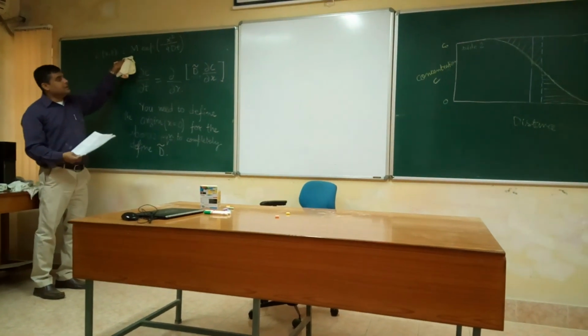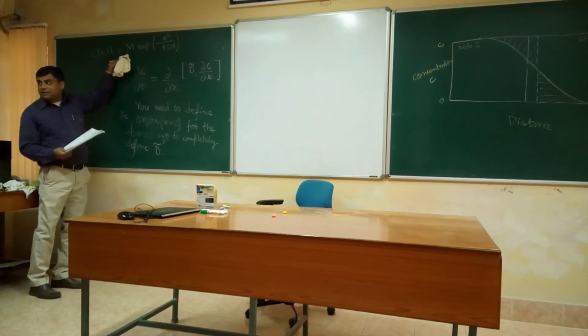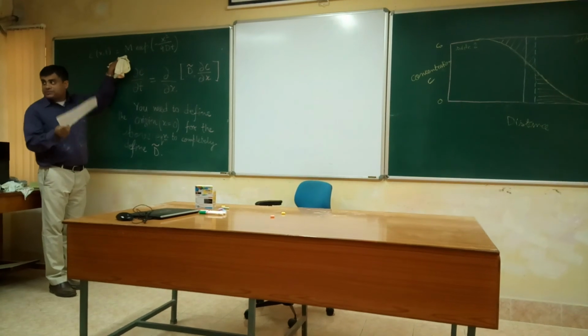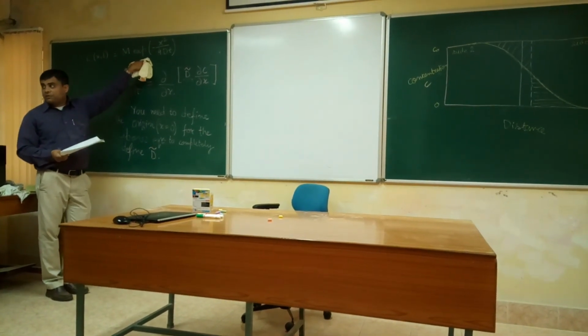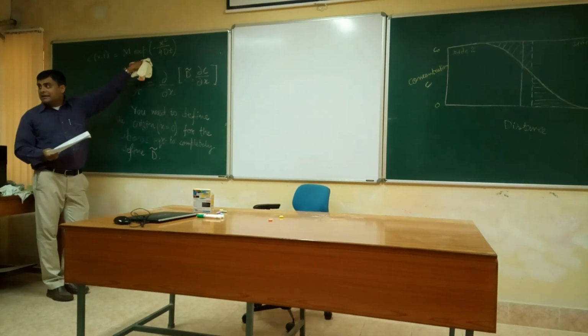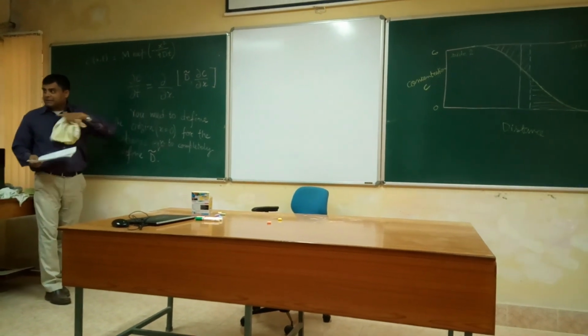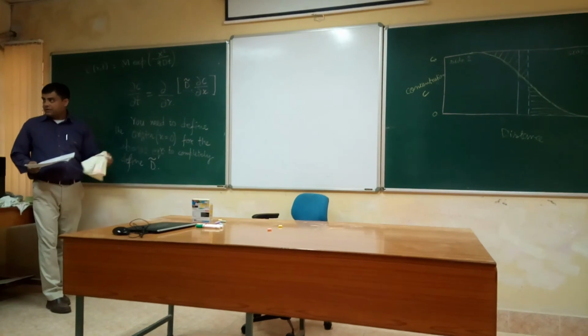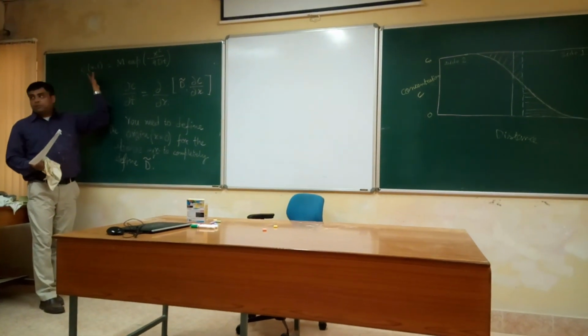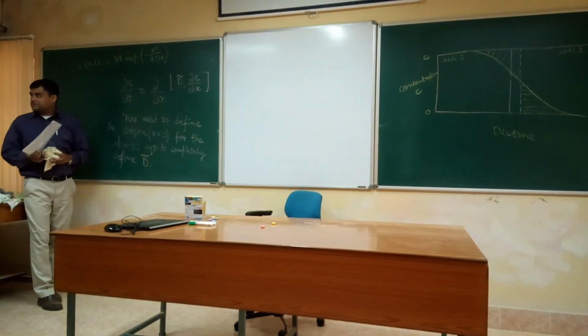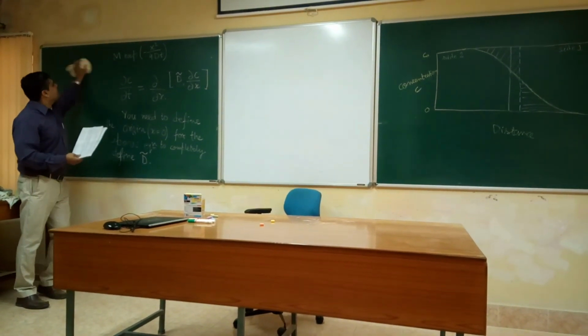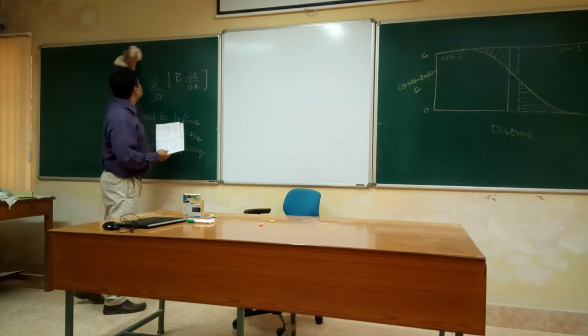That is given by the number of isotopes per unit area that you have put, multiplied by exponential of minus x squared over 4Dt. After annealing, you count C versus x, the C profile. From that, if you plot ln C versus x squared, from the slope you will get the self-diffusion coefficient. That is how the tracer or self-diffusion coefficient is obtained.